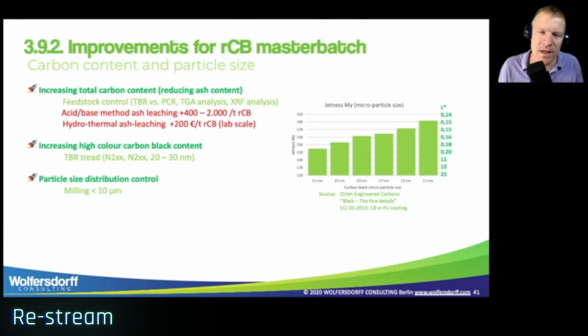issues. There's a new method, hydrothermal ash leaching. Hydrothermal meaning just with water and temperature. It promises to be cheaper, about 200 euros per ton, but that particular company is only at lab scale, and I find they first have to prove the commercial viability for a thousands of tons per year plant.